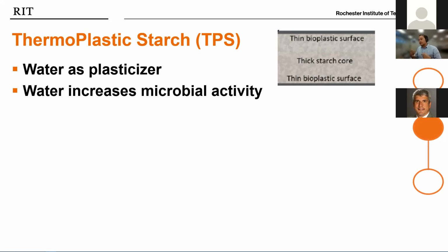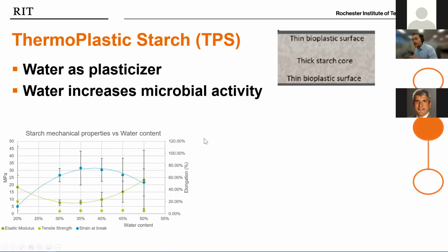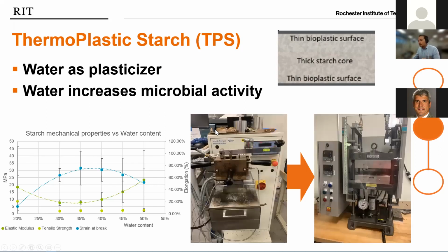But after meeting with industry and looking through literature, it's not very clear how water and the mechanical properties of starch behave. So we prepared some samples at different concentrations of water in a small mixing head and compression molding. And we found out that 45% water gave a good balance between the water content and the mechanical properties. The problem is that this produces very small amounts of thermoplastic starch. And if we want to make a lab scale film prototype, we need pounds, we need kilograms. So I had to find another way to make this work.